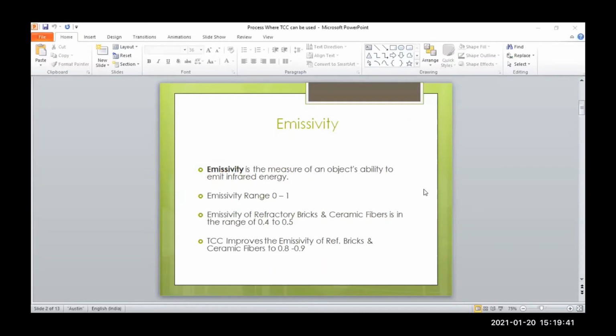Basically, our coating is a high emissivity coating, and we improve the emissivity of the refractory bricks and ceramic modules also. So emissivity is basically an object's ability to emit infrared energy back in the process. Whatever insulation you have installed in the furnace or ovens has certain emissivity, and the emissivity of refractory bricks and ceramic fibers used in furnaces ranges between 0.4 to 0.5. So if, for example, 100 units of heat is imparted on refractory brick, 60% of that heat will be absorbed and 40% of that heat will be re-radiated back in the process.